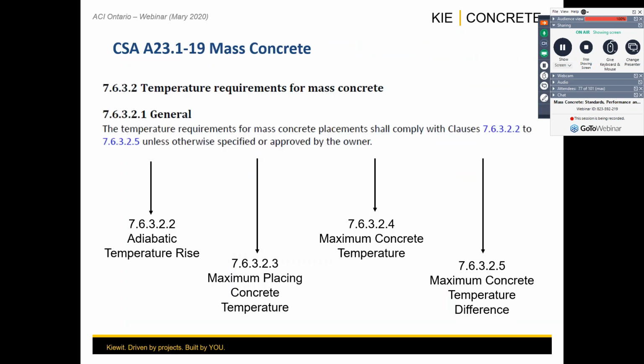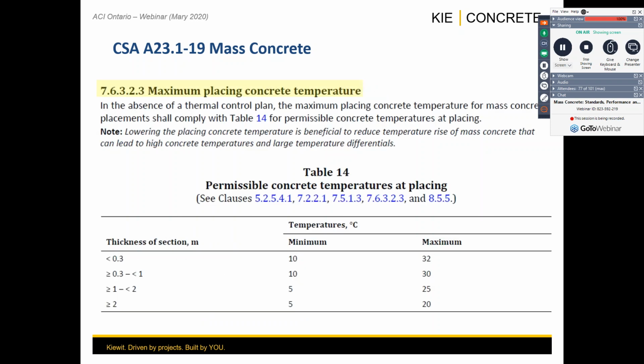Then we go to temperature requirements, in this case for maximum placing concrete temperatures. In the CSA 2019 version, we look at the maximum placing concrete temperature and how it relates to mass concrete and thermal control planning. If we have a thermal control plan, it's going to assess the temperature rise, assess the risk of exceeding temperature limits and temperature differentials, and determine the most appropriate placing temperature for your mass concrete. In many places, most likely in the summer, the default limits provided by CSA are not necessarily practical. So if you have a thermal control plan, you're going to be able to justify reasonable placing temperatures for mass concrete.